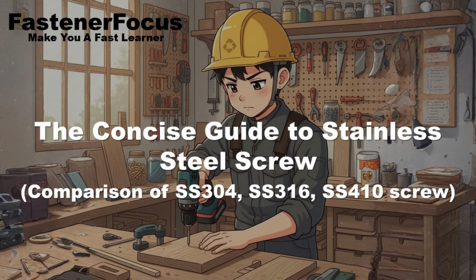I mean, is it really worth the extra step? Oh, absolutely measurable. A properly passivated 304 or 316 stainless steel fastener can exhibit corrosion resistance that is an astounding 5 to 20 times better than an untreated one. This is why passivation is mandatory for applications where pristine corrosion resistance is critical. Think food processing equipment, pharmaceutical manufacturing, and medical or surgical implants, where chemical inertness is paramount. It's really the highest standard of surface preparation.